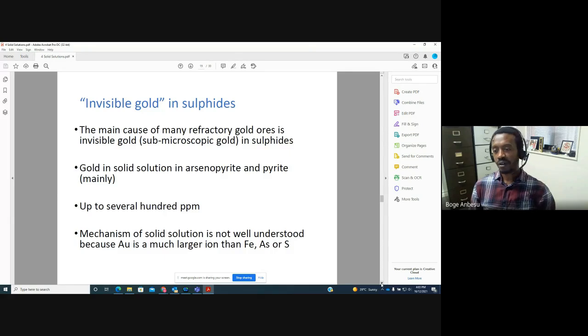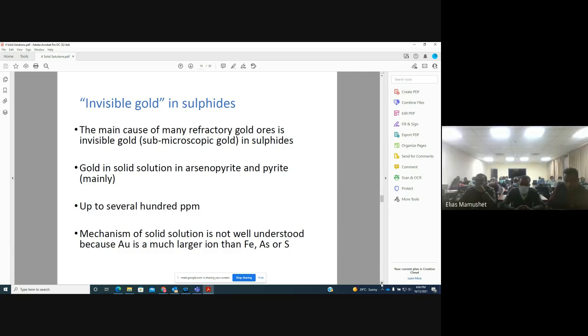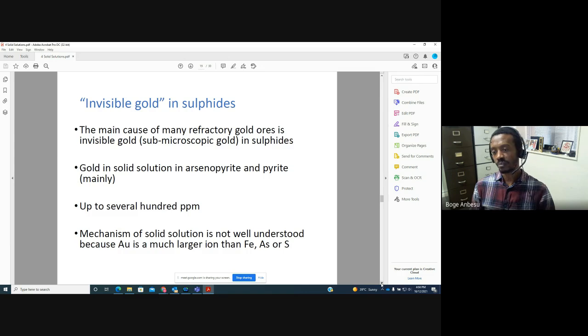Okay, so if you have gold in solid solution in sulfides, the gold tends to be very fine in size. It's almost atomic scale gold distributed in arsenopyrite, pyrite, and so on. So when you do assay, it comes with gold, so you have some gold in the sample. But when you do XRD, it comes as arsenopyrite. There's arsenopyrite, but there's gold. There's pyrite, but there's gold. So you need to do a very detailed quantitative analysis to work out exactly how much gold you have, if it's a gold deposit.